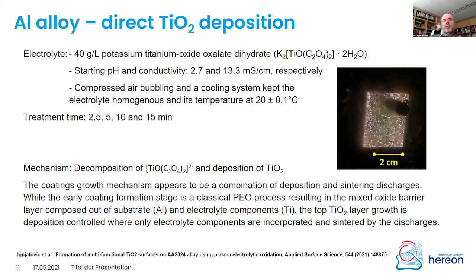And this electrolyte, what we have used here, the potassium titanium oxide oxalate dihydrate, a simple electrolyte, is not working for magnesium, but it works relatively nicely, as you can see also in the picture, which is taken from the process for the aluminium substrate. And here we have something new.